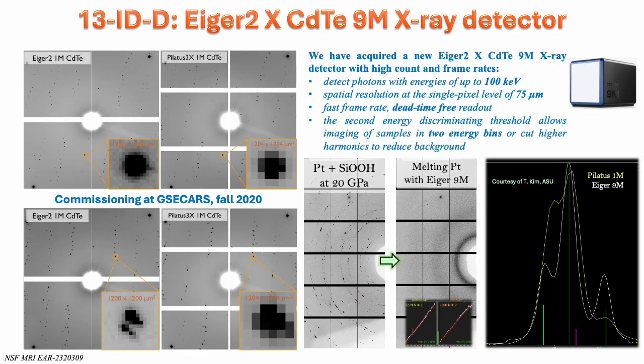To increase the resolution of our X-ray imaging, we have upgraded our Pilatus X-ray detector with a new cadmium telluride 9M detector that has a much smaller pixel size, only 75 micron, and it has a dead-time free readout. You can see the clear difference between the new detector and the Pilatus detector. The first experiment that we did after the APS upgrade was an easy combination of laser heating with this detector. We can immediately see the melting of the materials. And when we study the perovskite, you can clearly see the triplet splitting on the perovskite peak, compared to what we had before.